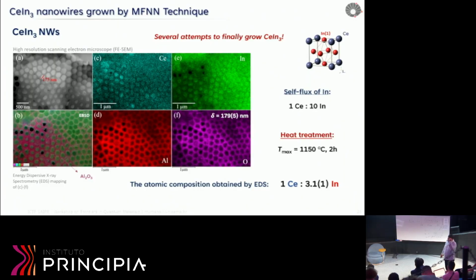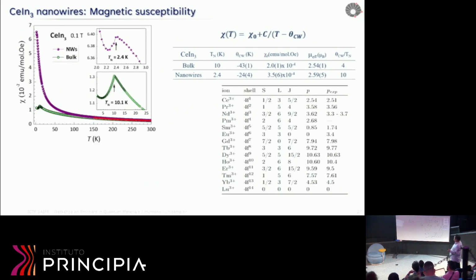This was a hard time for us because it took several attempts to finally grow. It's not perfect yet. I mean, we got the correct phase, 1 to 3 cerium indium, everything all right here. If you look at this, you have cerium in the pore, indium in the pore, and outside, aluminum and oxygen. This is the alumina outside the pores. Everything worked fine. It's cubic, but then we start to characterize these materials.